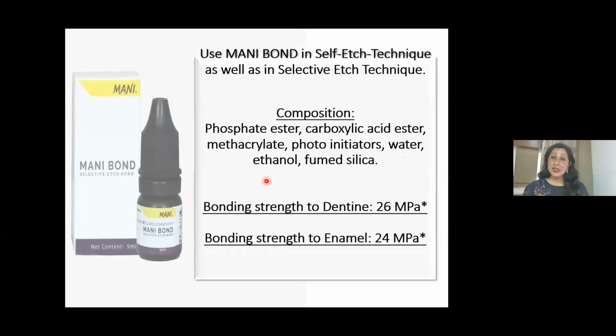It can be used in self-etch and selective etch technique. The composition is, there has to be an acid, a mild acid in your one component bonding agent, so that it can etch the enamel and dentine. Here it is the phosphate esters and the carboxylic acid esters which do this job, and they are quite mildly acidic, pH less than 2. That's very good, because you need an acid which doesn't have a very acidic pH, to not have a deteriorating effect on enamel and dentine.